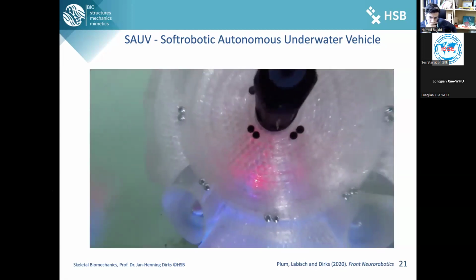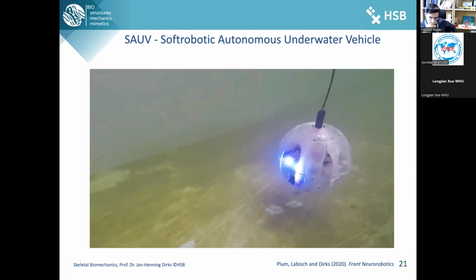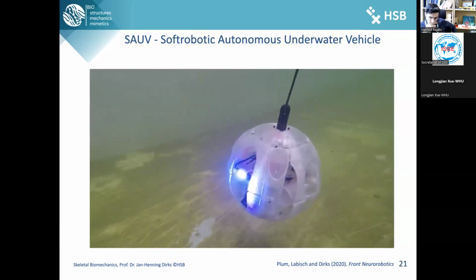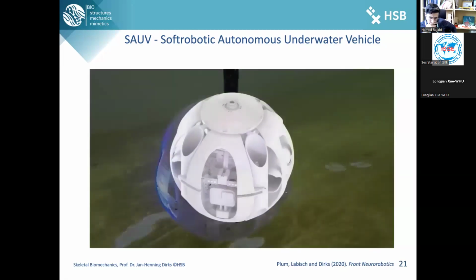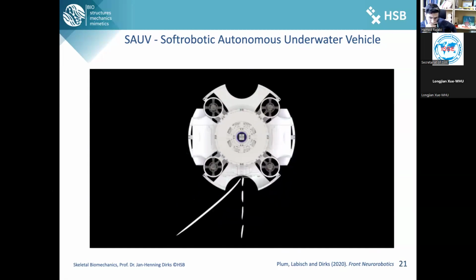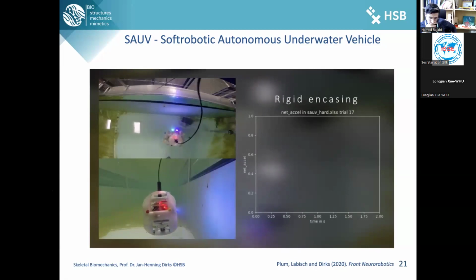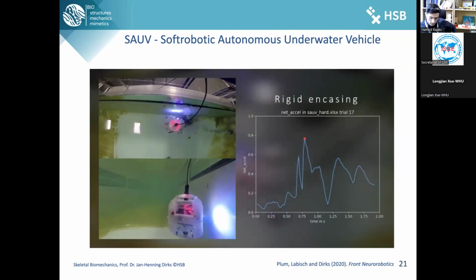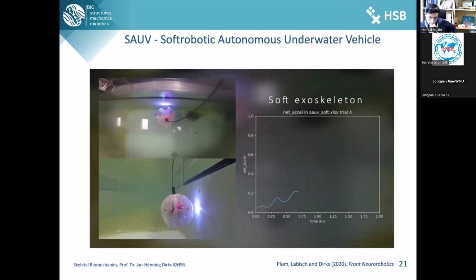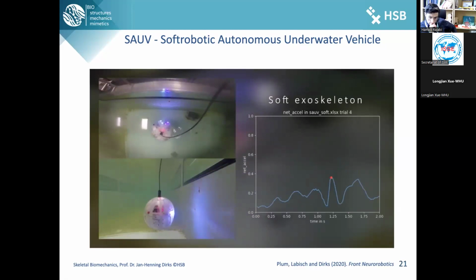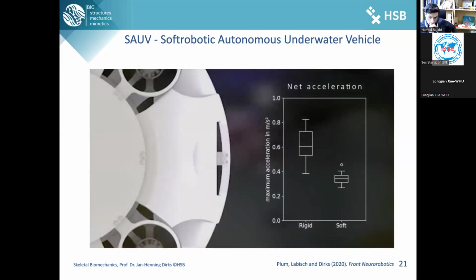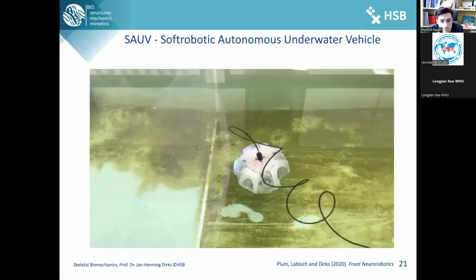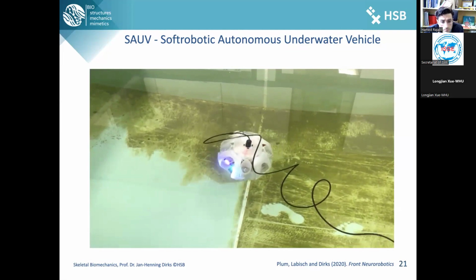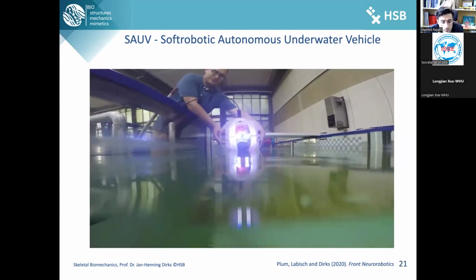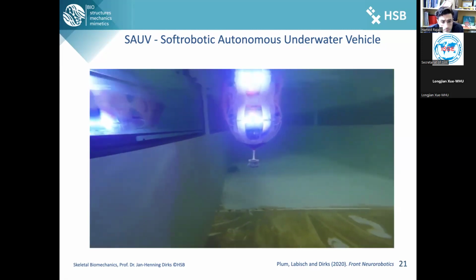In our prototype, the soft exoskeleton is entirely 3D printed using a thermoplastic polyurethane. Contributing to the spherical design, the thruster ducts are elongated and created from the same material. As the spacing allows for multiple cameras to be attached, the exoskeleton prevents impacts from causing damage in any direction without limiting the camera's field of view. Our experiments have shown that the installed soft exoskeleton significantly decreases the stress on all components by measuring the net acceleration during multiple impact trials. Even when operating at comparably low velocities, the exerted forces resulting from an impact are reduced by 50%. As the exoskeleton does not affect the maneuverability of the system and has a negligible effect on its buoyancy and maximum velocity, it has proven to be a versatile solution for any type of underwater application.